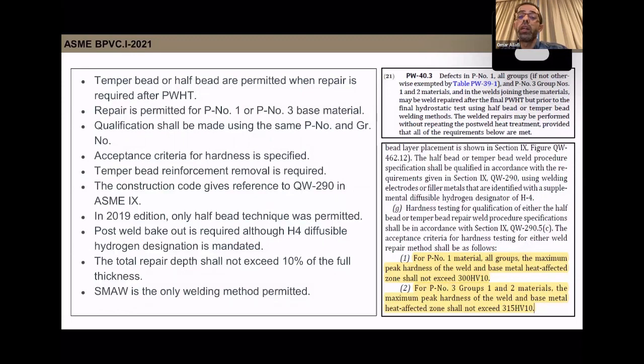So here, the total depth shall not exceed 10% of the full thickness, and post-weld bake out is required, although H4 diffusible hydrogen designation is mandated. So they're mandating using H4 hydrogen designator, and they're mandating the post-weld bake out to reduce the likelihood of hydrogen-induced cracking. This post-weld heat bake out is a non-essential variable in QW-290.4.